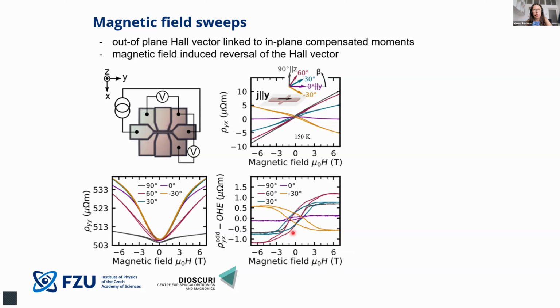So it simply points to the fact that it cannot be some magnetic field induced effect. It cannot be an effect which, naturally, when you apply a magnetic field, counts the spins and generates some sort of effect. No, here we have the effect clearly present in zero magnetic field with this hysteresis. The second important thing is that the hysteretic loop is closing at the field which we know is the spin flop field. So it fulfills the properties of manganese telluride. It can be linked basically to manganese telluride.